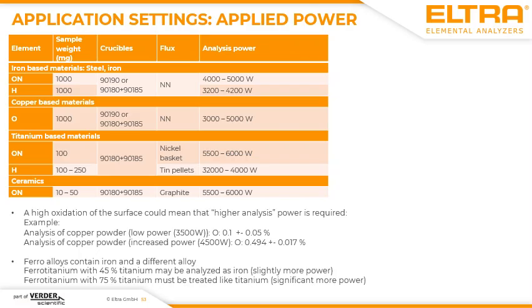And here we have a summary of used crucibles, used flux materials and applied power for typical base samples, meaning iron-based samples, copper-based samples, or titanium-based samples. When you have a look at this table, I also would like to give you the hint that it may make sense to increase the applied power for your sample when it is powder-shaped. I had, for example, a customer who processes copper samples at typically 3500 watt and got good and repeatable results. Then he got powder-shaped samples once, and nothing happened, and he did not get repeatable results. This is due to the fact that this powder sample has a very high oxygen concentration, and the analyzer was not able to process this high sample weight with this applied power. So this does not fit together.